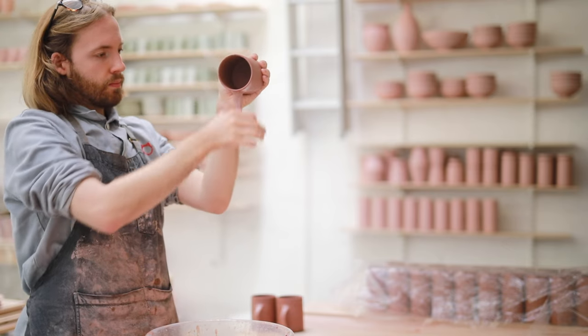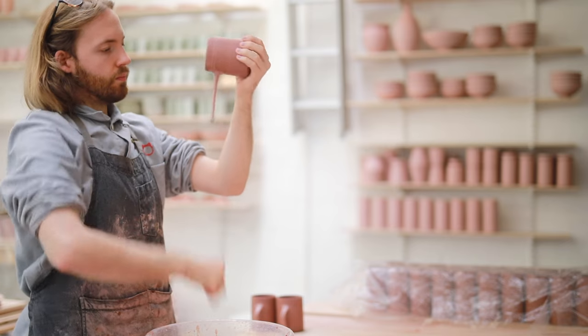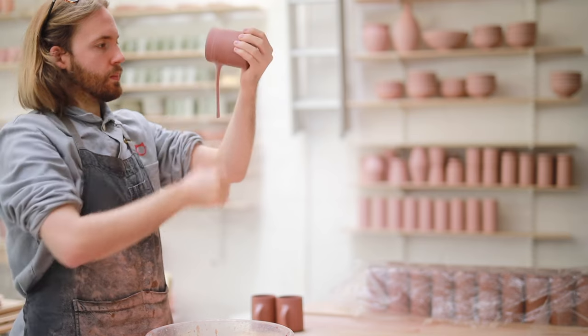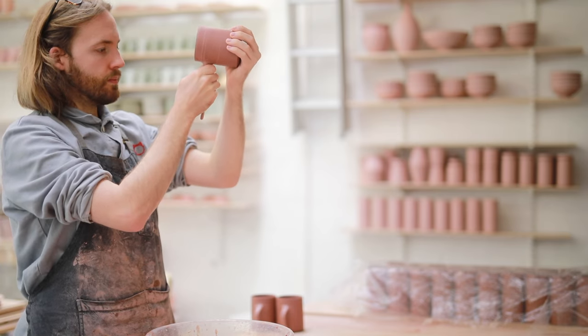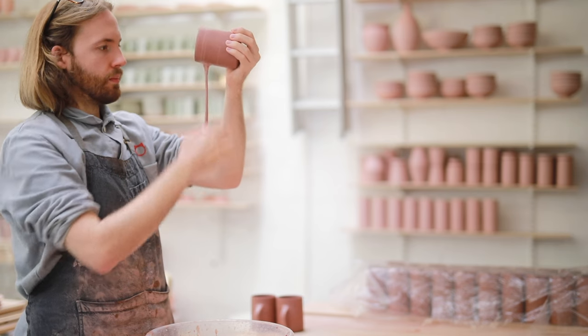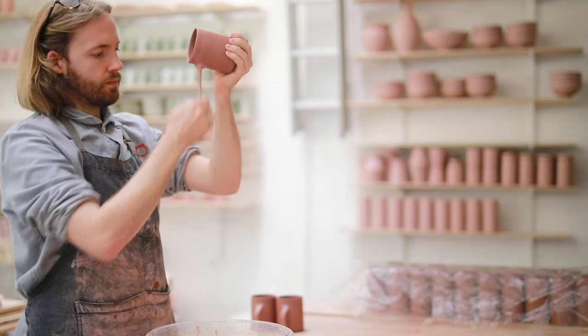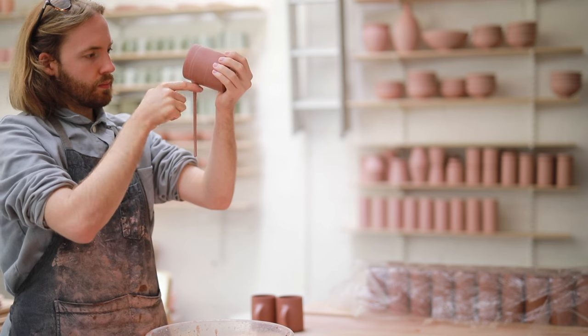With each pull of the clay I try to get my hand as high up on the handle as possible, right up close to where the mug wall is. Once there, I squeeze and pull throughout the entire length of the handle all the way past the end. You don't want to release the pressure too early — if you do, you can end up building a lump at the end of the handle, and as this lump grows you'll eventually pull into it and tear away the whole thing.